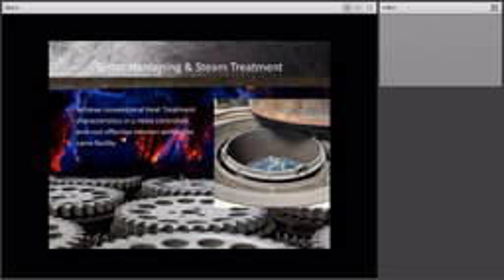Another opportunity is with steam treatment. Steam treatment increases the hardness slightly on the outside of the component because it places a steam oxide coating where a high pressure steam oxide is introduced to the surface. Steam is introduced, the oxide forms, and you get that blue colored component that has a slight bump in hardness and a little bit of rust inhibition.